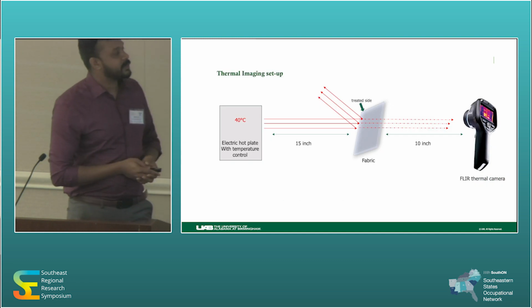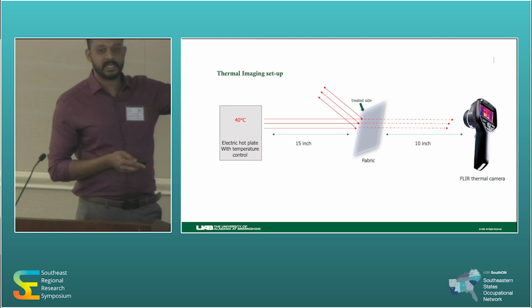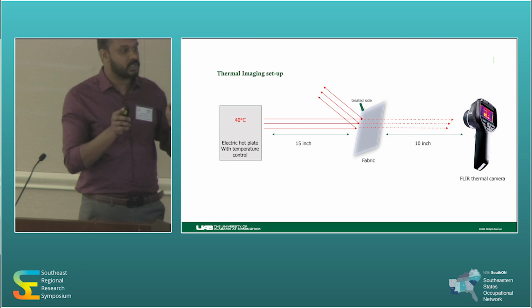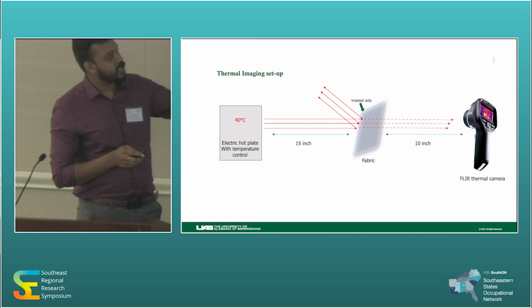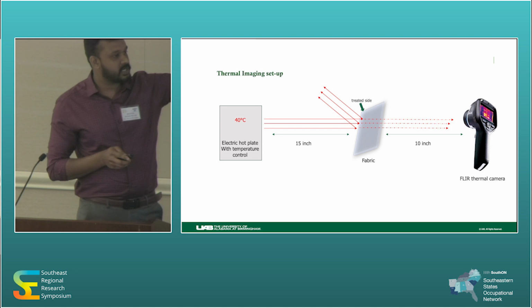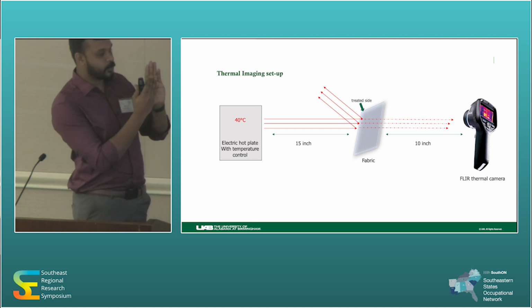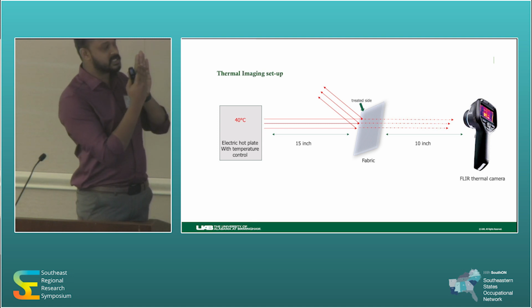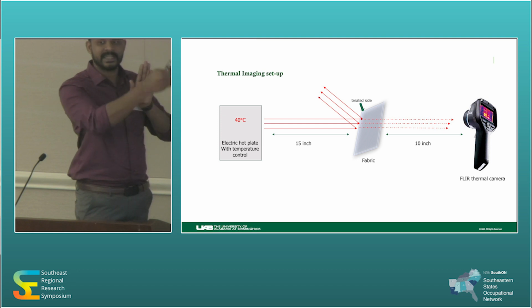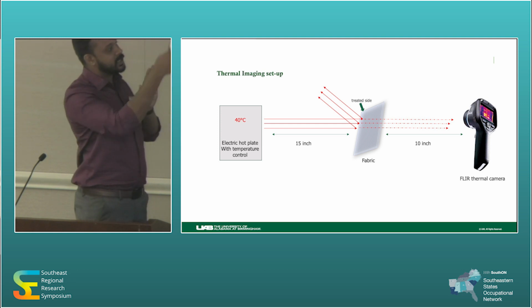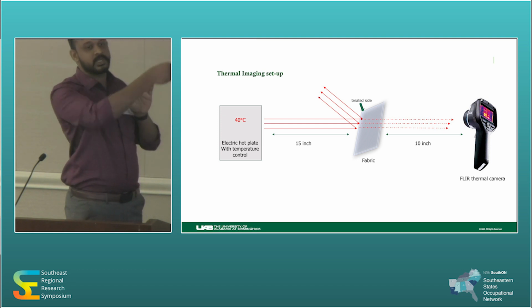So this is the thermal imaging setup. We have a 40 degrees C temperature controlled platform, and from there a 15-inch gap to the fabric surface, and the thermal platform is facing towards the treated surface of the fabric. Then from there, a 10-inch gap to the thermal camera.